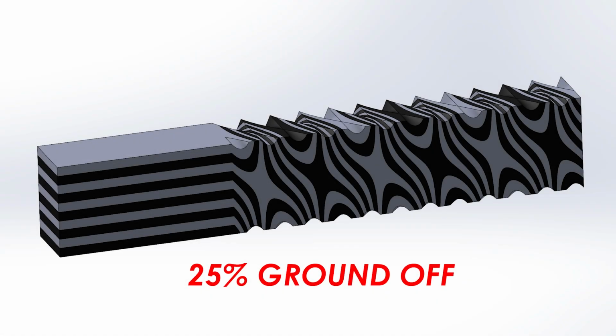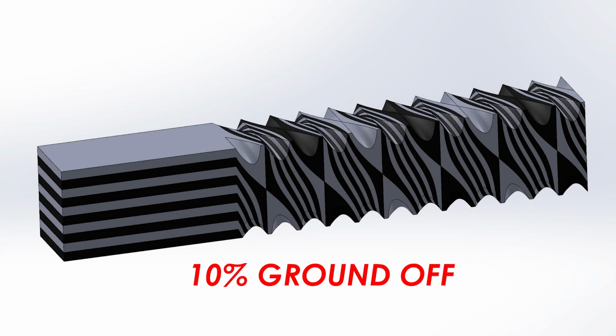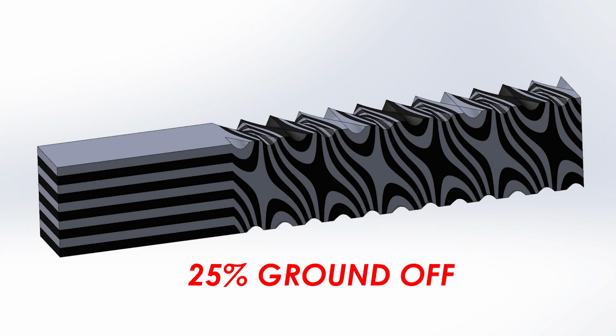Now I have taken 25% off the surface, and we see a pattern that can also be seen in the blade. This here resembles a twisted cross. The conclusion is that the smith took mostly 10% off to create the chevron pattern, but occasionally his grinding went deeper to about 25% or more. This didn't happen by mistake.